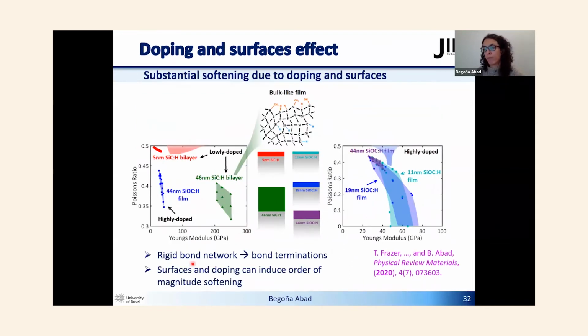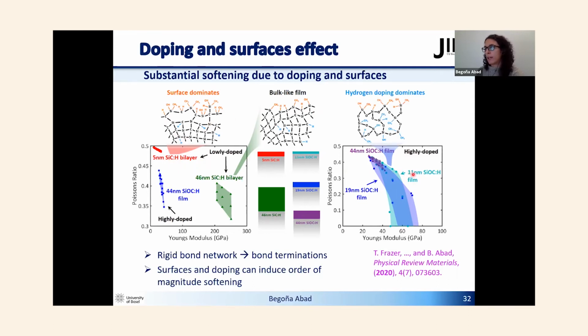We explain this from a rigid bond network point of view. If we look at the bilayer, it is 46 nanometers, which is still thick compared to the 5. If we look at the rigid bond network, we see that the bond terminations from the surface are not enough to affect the mechanical properties. But when we are in a very thin layer, these bond terminations given by the surface really affect our mechanical properties, creating this softening. On the other hand, this high doping is actually hydrogen doping. When it dominates, it disrupts the bonds within the network and also creates this softening of the mechanical properties. So both surfaces and doping can induce an order of magnitude softening.